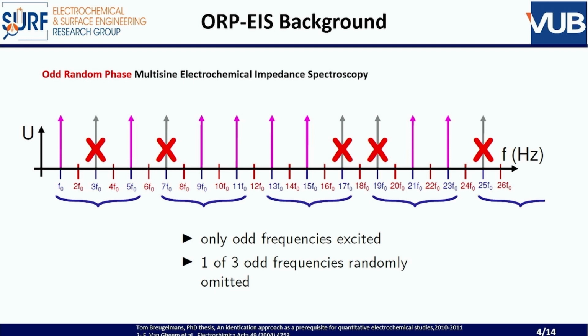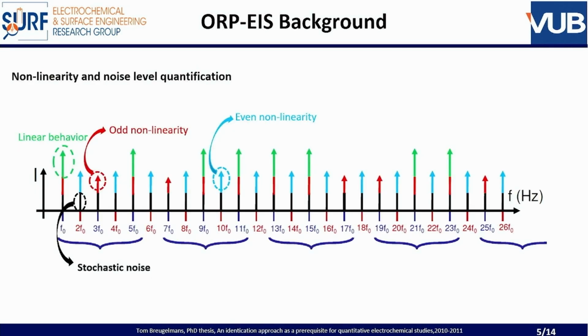If you measure at these frequencies and you have a signal, it means that you have a nonlinear system. This is the way we try to figure out whether the systems behave linear or nonlinear. Here you see a little bit how we do that. By measuring at some frequencies, we can even look at odd and even nonlinearities. And by comparing the measurements, we have access to the noise. This is also very important because it's completely neglected in a lot of measurements.